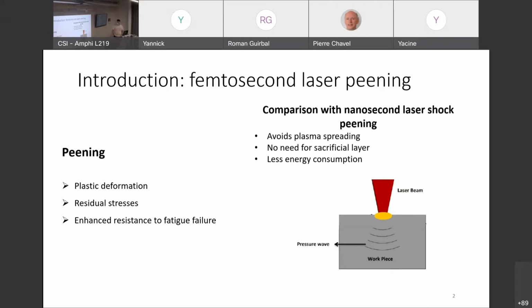The interest of femtosecond laser peening in comparison with the nanosecond is that it avoids the plasma spreading during the shock. So there is no interaction between the laser beam and the plasma. As a consequence, there is no need for a sacrificial layer on the material. So this could allow some new techniques. And last, it consumes less energy than a nanosecond laser.